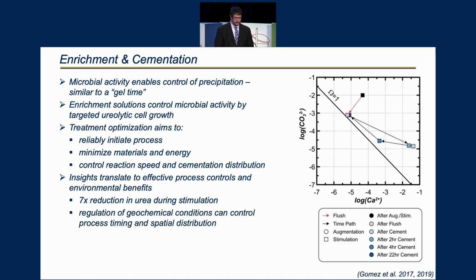Upon transitioning now, we can also think about how we can regulate geochemical conditions in order to carefully control process timing and cementation spatial distribution. We can see, as illustrated in this diagram, which is an activity ratio diagram, we can compare solution carbonate and calcium concentrations to the solubility of calcite mineral, which is shown as the omega equals 1 line, or the solubility of calcite. As shown, after stimulation in this flow diagram, we see that we have high concentrations of carbonate resulting from the hydrolysis of urea, and these can be removed prior to starting the cementation process through flush injections, which aim to remove reactive species and prevent issues such as well clogging.